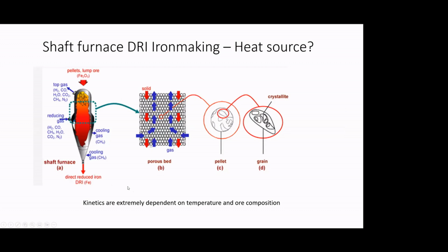So these are made in a shaft furnace, which is like a small blast furnace, with the lumps feeding through the top and reducing gas. There's a bed of lumps at the bottom, and the gases pass through that and reduce the ore on the surface. But it's very dependent on temperature, so the kinetics are very complicated, and that's complicated by the differences in ore composition and impurities. And in the case of hydrogen, because it's an endothermic reaction, you need to add heat, and the reaction is changing all the time, so it's very hard to control the temperature profile in that reaction.